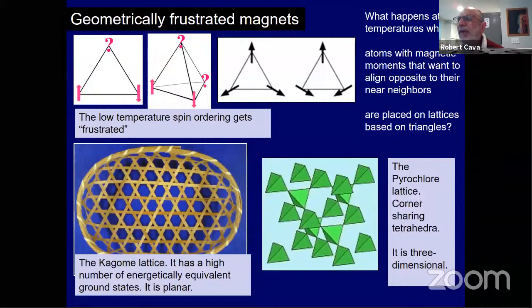And here's a picture of a Kagome basket and something about how the pyrochlore lattice is related to the Kagome lattice. You just take this Kagome, which is corner-sharing triangles, and you put a vertex on the top of every triangle, and you get a tetrahedron, and then the tetrahedra share corners to make a pyrochlore.